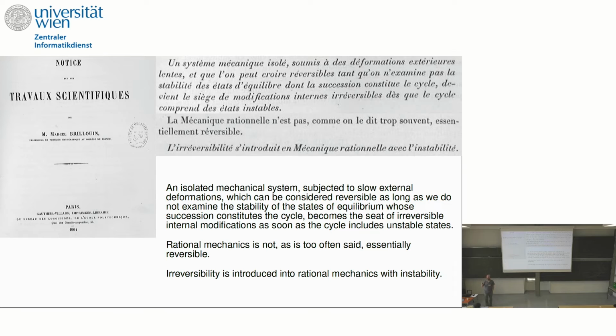So he has an argument where you look at the problem of two magnets, and you approach a magnet; basically he's looking at a bistable system. And he showed that if you have a bistable system, you can drive slowly and you have a reversible response. And if you drive more, at some point you have a jump, and then you lose reversibility. The paper on friction was in 1899, and he was saying: an isolated mechanical system subjected to slow external deformation can be considered reversible as long as we do not examine the stability of the state of equilibrium. So it means we are looking from the microscopic viewpoint from far away, and it becomes a seat of irreversible internal modification as soon as a cycle includes unstable states.